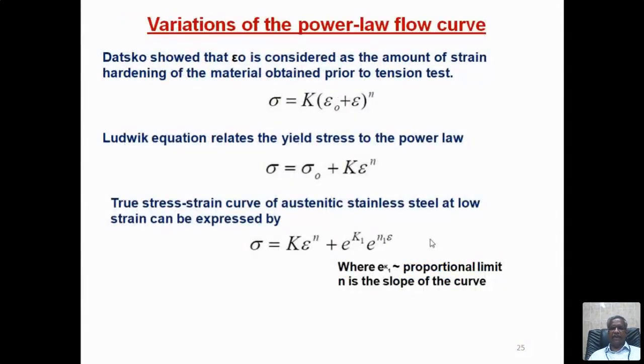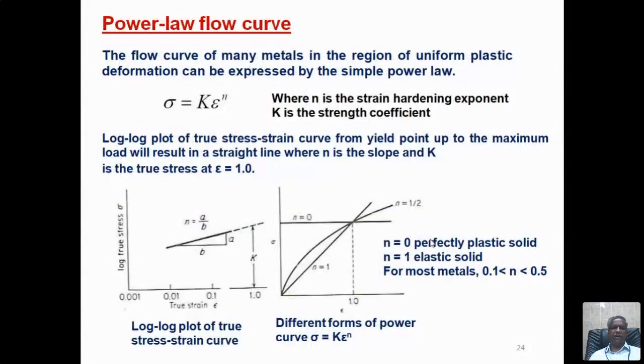So there are different variations of this power flow equation. Modifications were done by further researchers. One of the equations is the Ludwik equation, where they have added k epsilon power n plus the yield stress, sigma naught is the yield stress. Similarly, for austenitic stainless, for each material, for different structures, you can develop the equation. But the base equation is sigma equal to k into epsilon power n, the power equation, the flow curve equation. It is the governing equation for the true stress, true strain curve.